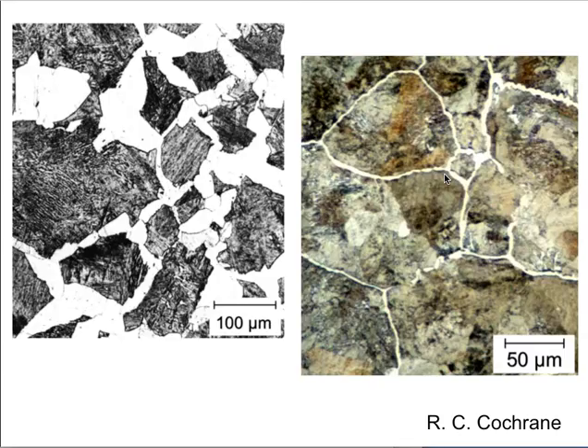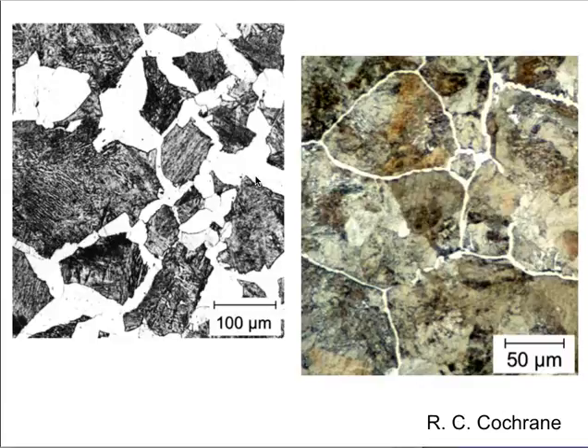This is what allotriomorphic ferrite looks like - you have come across this many times. These are layers of ferrite because the ferrite nucleates at austenite grain surfaces; it is heterogeneous nucleation and they look completely clean. There is no internal structure within those layers of ferrite - it is just grains growing and consuming the austenite and destroying any defects in their path.